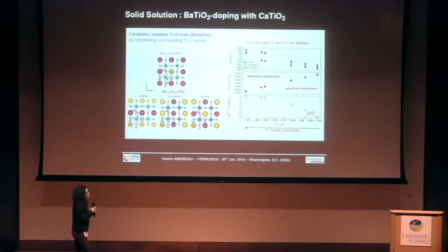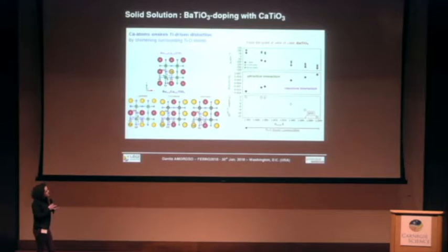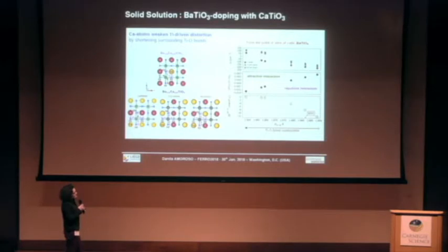And we know, we also proved, that the dynamics of barium titanate is strongly sensitive to this volume contraction. In fact, we see that the interaction between the titanium and oxygen atoms changed from destabilizing to become stable with the contraction of the titanium bond lengths. And in fact, the polar instabilities disappear with this volume contraction, as well as, accordingly, the energy gain of the polar phases.